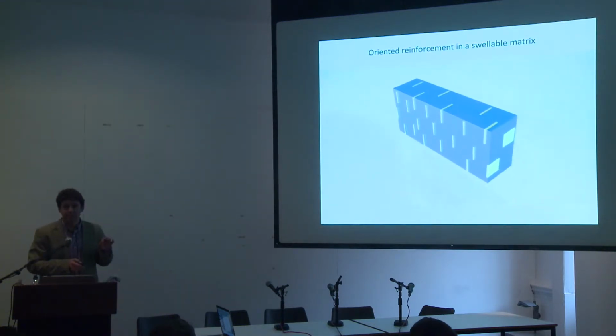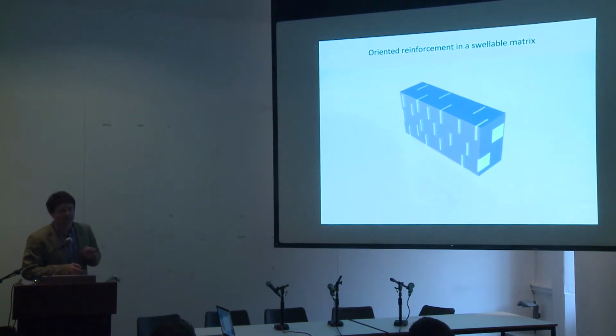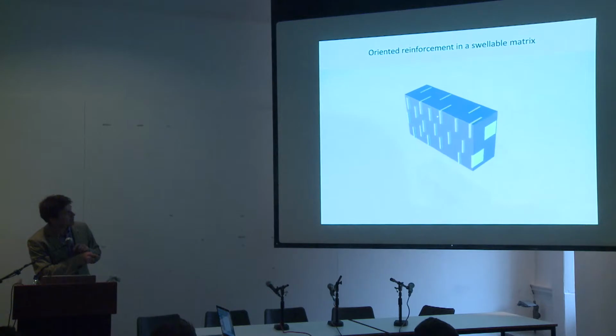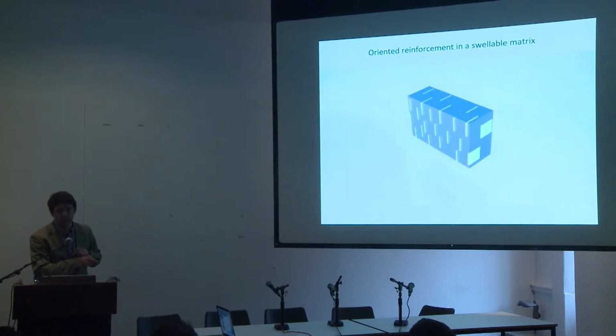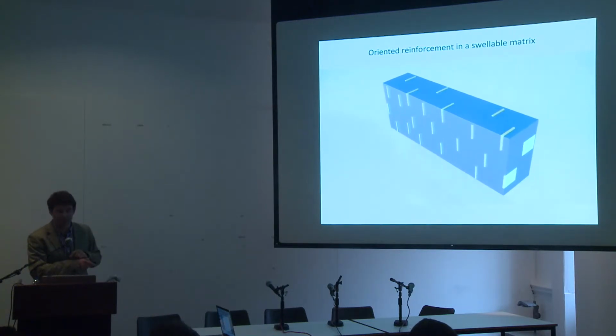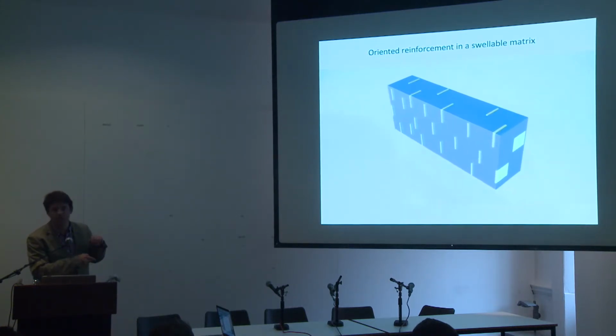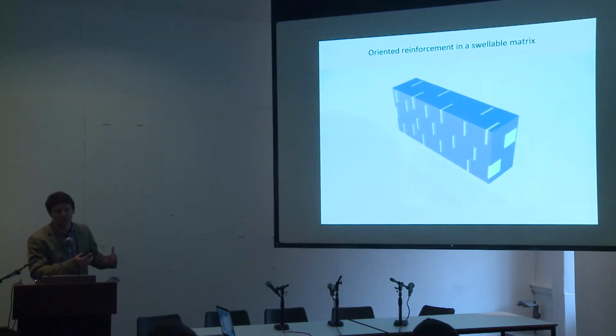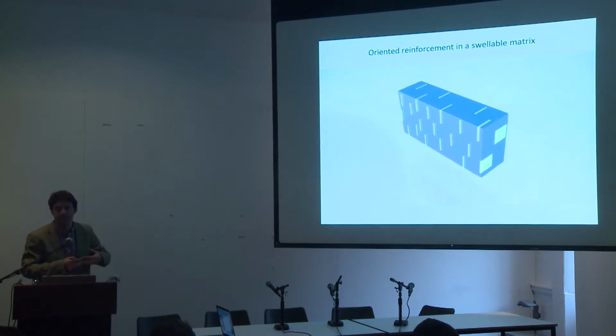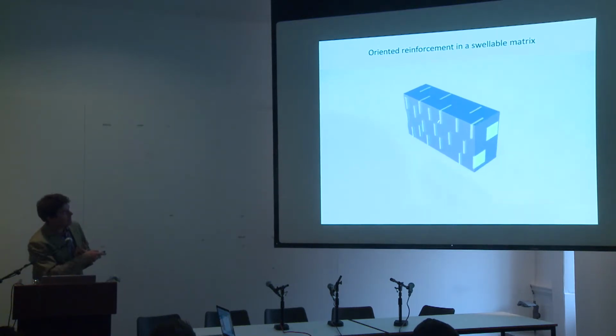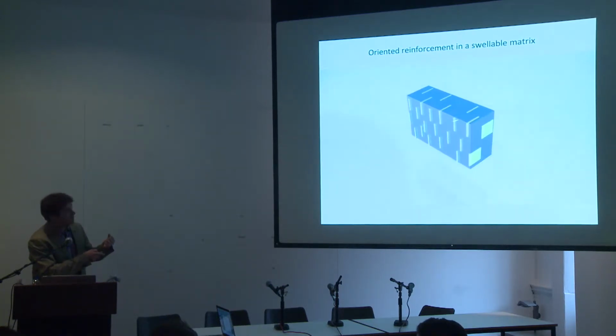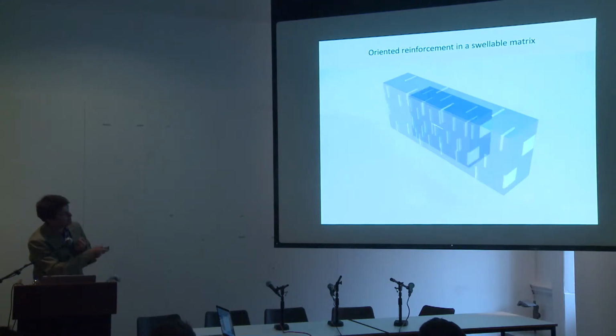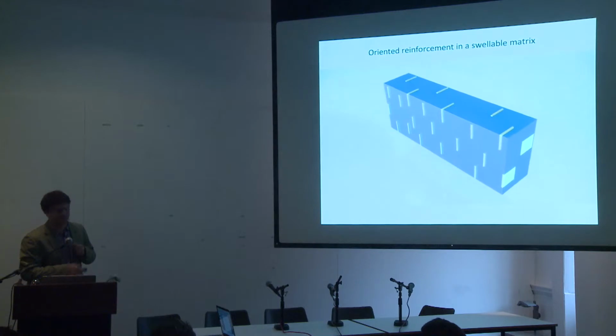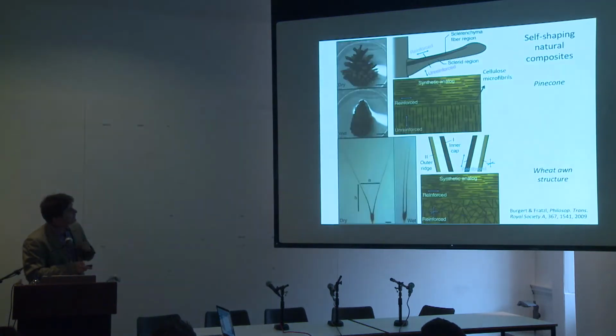So the design concept behind all these structures is very, very simple, and that's illustrated in this cartoon. What you actually have is a certain reinforcement. In nature, it's mostly cellulose fibers. Here I'm representing it as platelets. This reinforcement is oriented in one particular direction, and then you have a continuous matrix around it, which is responsive. In this very simple example, it just expands, takes up water, and swells. But because this matrix is mechanically constrained by the reinforcement, swelling will happen preferentially 90 degrees to the direction of the reinforcement, but not in line with the reinforcement. And that is the very simple idea behind many of these shape-changing structures in nature.